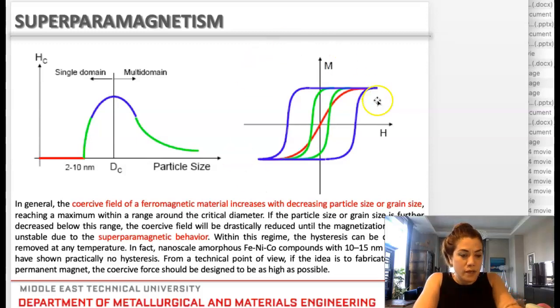Interestingly, certain materials, for example this blue one, let's call it a ferromagnetic material, and this ferromagnetic material is a hard magnet, right, because it's very large. But as I play with the material's grain size, making it either a single crystal or smaller crystal, depending on the particle size, as you can see here, either single domain or multi-domain, of course, we can play with the materials, how hard, how strong of a magnet it is, or how soft of a magnet I can make. Same material, just playing with the structure of it, how big my crystal domains are. Look, not magnetic domains, crystal domains, right? How big are the grain sizes?